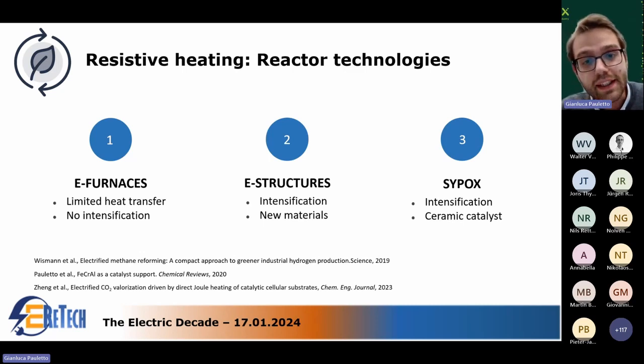Another solution would be taking a material that is electrically conductive, using it as a catalyst support, and then applying electricity. In this way, you are using the catalyst support both as a catalyst carrier as well as a heating element, and you would be able to achieve a very high intensification. You are decoupling the heat transfer from the heat flux through a wall of a reactor. On the other side, you are usually combining a metal, an electrically conductive material, together with a ceramic that is usually a catalyst. So you have this combination that needs to be properly tuned to be stable.